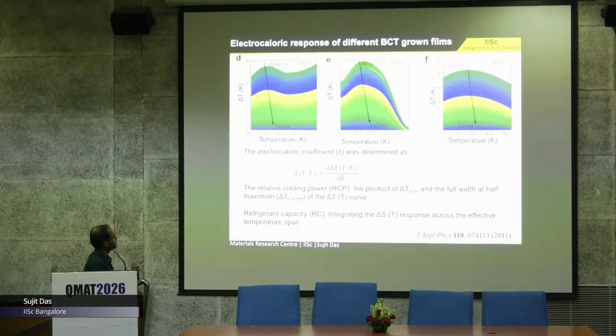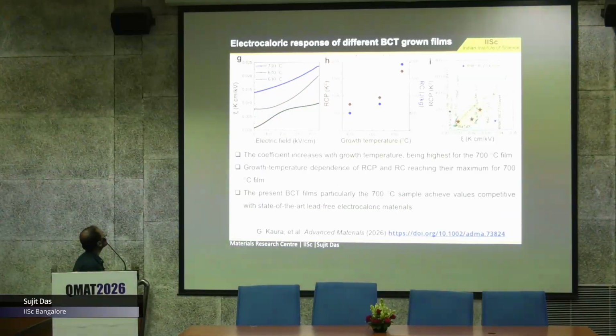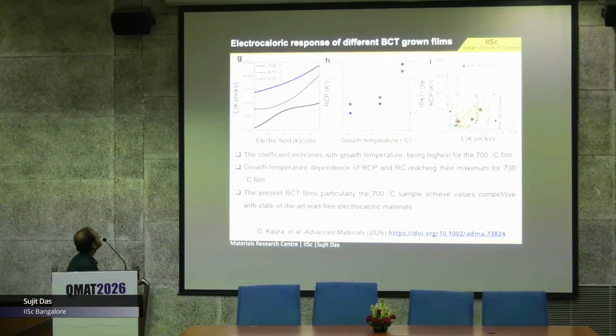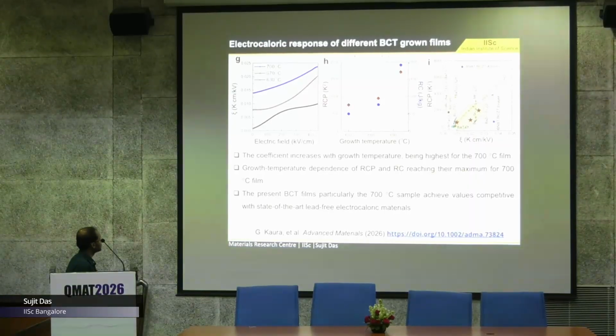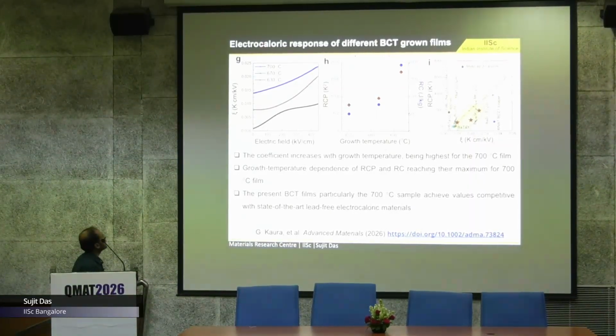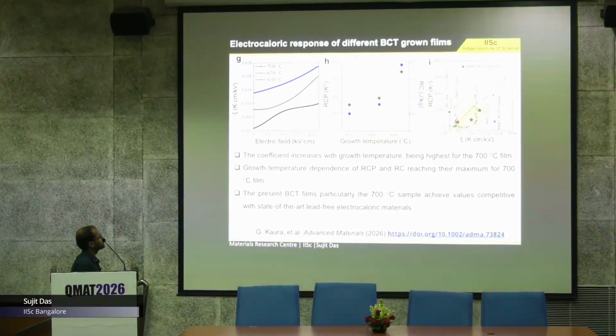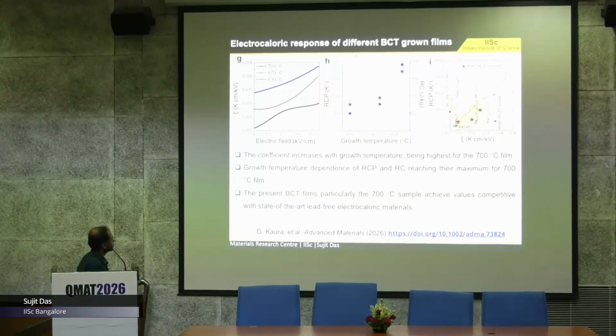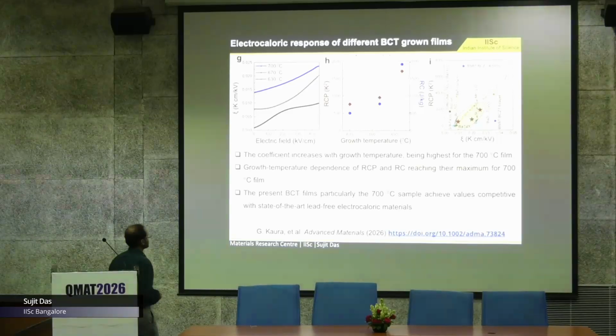Then we calculate the electrocaloric coefficients using these equations, and also the relative cooling power, RCP, which is a product of delta T max and the full width at half maximum of this curve. The refrigerant capacity we also calculate, integrating the delta S response across the effective temperature span. And if we calculate all of these, we found that the electrocaloric coefficient is highest for the films grown at 700 degrees C, and RCP and RC are also highest for 700 degrees C. We compare with the existing literature and found that particularly the 700 degrees C film shows a competitive value with state-of-the-art lead-free electrocaloric materials.